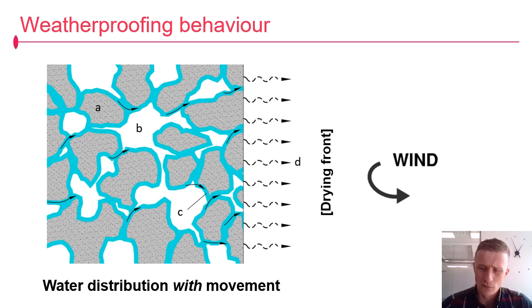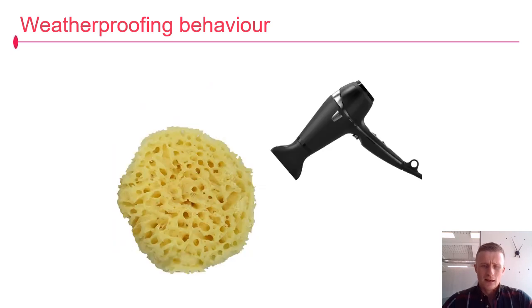That opens up a bit of free space of wettable solid surface. The next magnetic marble in the queue bumps forward to stick to that, but because he's coherent to his pal behind him, he bumps forward as well, sticking to him, and the whole chain of marbles starts to roll through the material towards the drying front. That's capillary drying, okay, non-saturated capillary flow towards a drying front. In other words, you take a wet sponge and blow a cool hairdryer across the surface of it, you'll find the whole sponge dries out, not just the surface, and that's because you get capillary flow through the material.